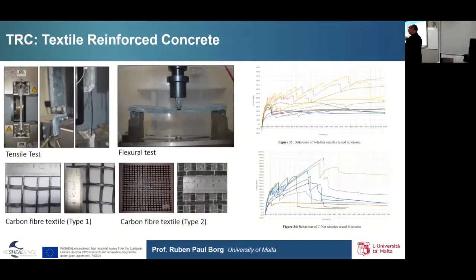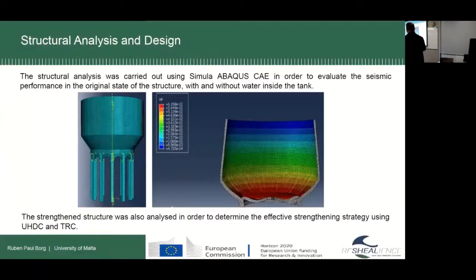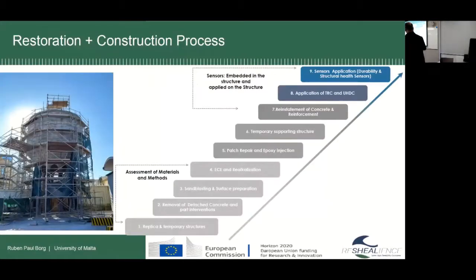Then to retrofit the drum, a different technology was used because it was too difficult to build a scaffolding in which the fluid material could be poured. So we used a textile reinforced concrete, which was highly thixotropic, so we could apply it without formwork by hand, and there was a carbon textile reinforcement for corrosion resistance requirements. Then once the materials were selected, the retrofitting was designed with a structural analysis. You have to identify the stresses that you expect and that the material has to withstand. So we went up to this.